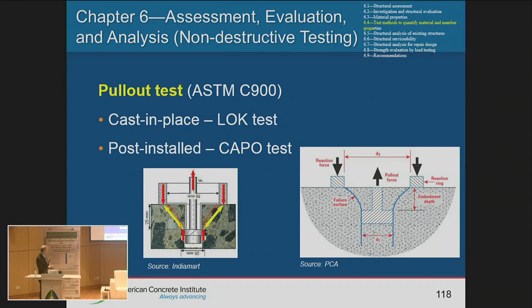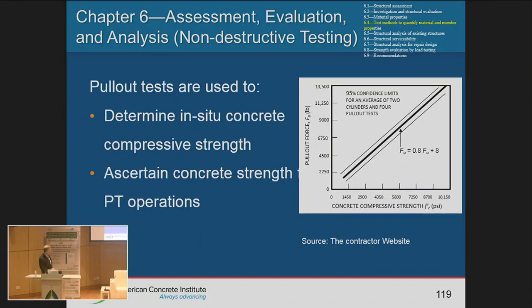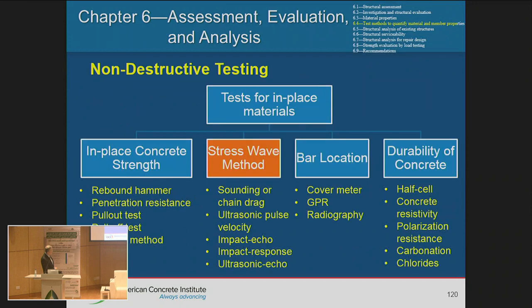Or you can have the pull-out. The pull-out is used in new concrete if, for example, you have post-tensioning to get your concrete strength, or a post-installed one, which is called CAPO, where you drill, then extend your drill inside and enlarge it. Then you have this expandable cylinder device that you let go through that hole, and when it reaches that enlargement, the expandable head will expand and hit against those pockets, and then you can pull and you'll get your concrete strength. So there are different methods of determining the concrete strength. And there is the chart that you get from the manufacturers, which will determine your pull-out force, and that will reflect your concrete compressive strength.